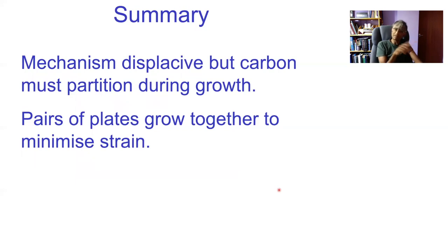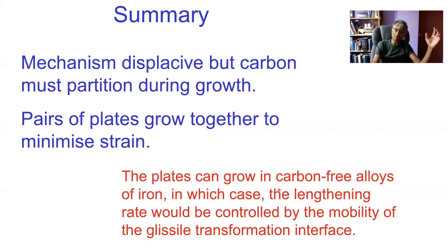I mentioned to you when we were selecting the tip radius which gave us the maximum growth rate, that ideas based on interface stability, that a flat interface in effect breaks up into waves, and those are our plates of Widmanstätten ferrite, is essentially an incorrect hypothesis because the morphology is determined entirely by strain energy. And the interface stability idea doesn't work anywhere because we can get Widmanstätten ferrite forming in carbon-free alloys where there is no diffusion. So all the mathematical models, for example the phase field models and so on, which talk about interfacial stability, are incorrectly founded as far as Widmanstätten ferrite is concerned.